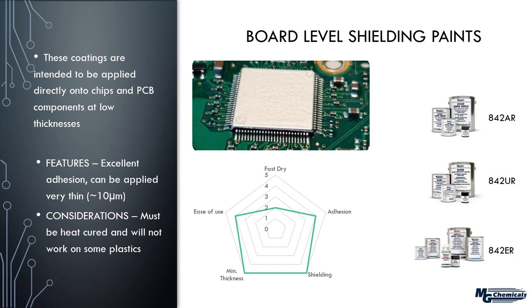So these have excellent adhesion, and typically they can be applied very thin. I put about 10 microns, but realistically, you could probably push around 6 or 7 microns. So that makes them very ideal materials. However, the one caveat I should mention is that these must be heat cured, and some of the heat curing temperatures are exceedingly high, and so that actually rules out certain types of plastics that may warp at these high temperatures. So just something to think about.